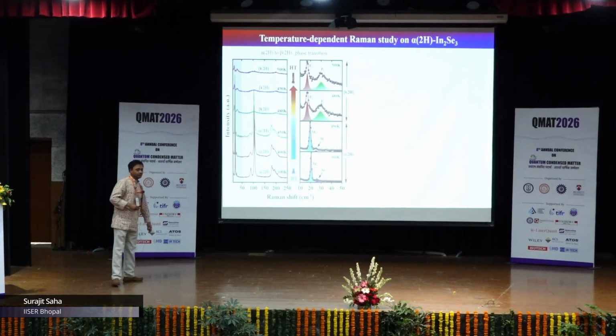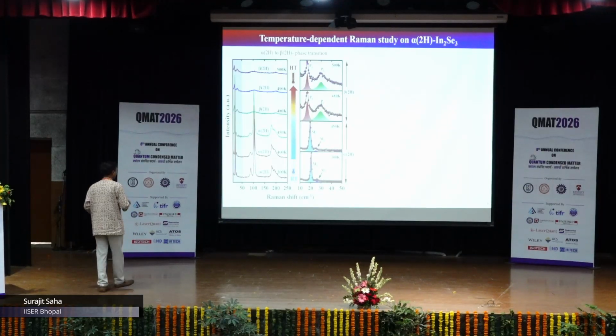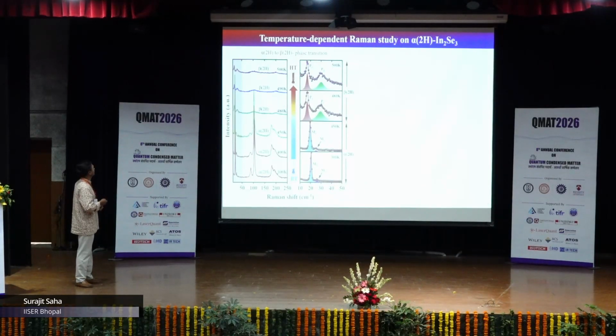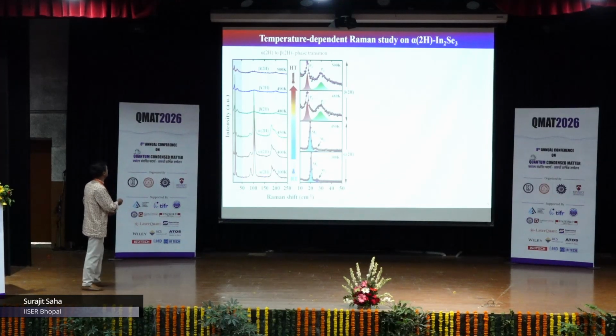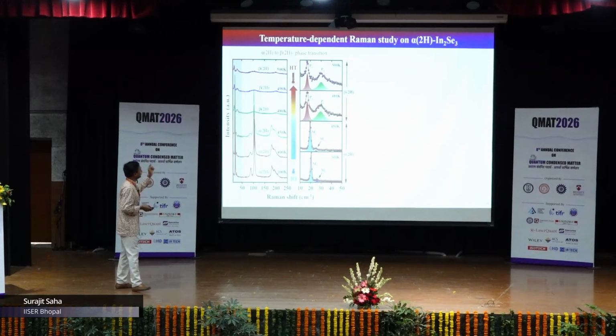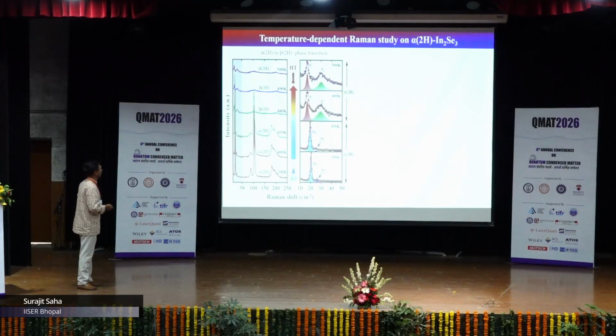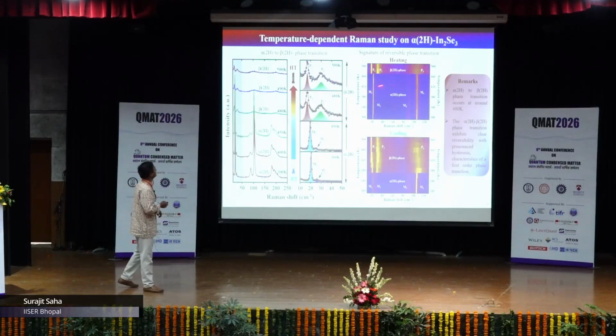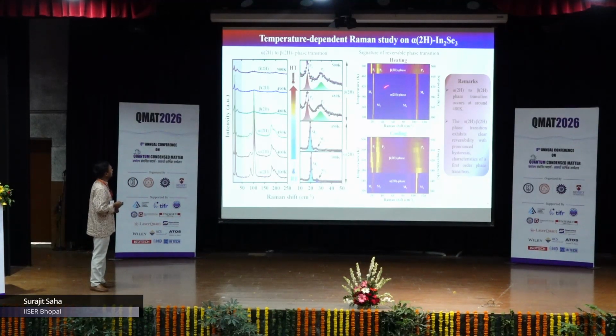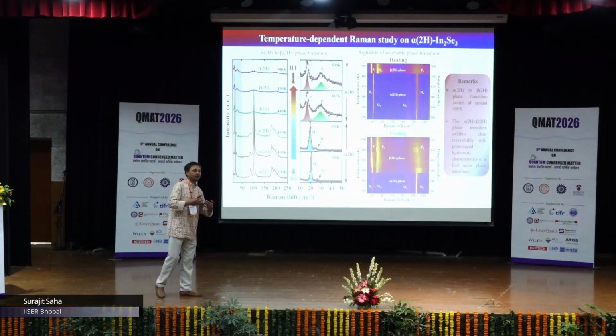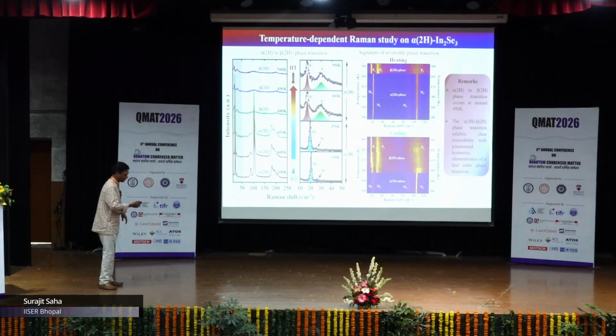the transitions. So we start from the room temperature stable phase, the alpha 2H phase. And as we heat this up to about 480 Kelvin, it starts to undergo the phase transition to the beta 2H phase. And if we limit our temperature to about 500 Kelvin, it retains the 2H phase. And if we cool down from that temperature, it comes back to 2H. Now there is a hysteresis. Here is the color map to look at this very clearly. So this is the heating cycle. You can see at about 470 Kelvin, the phase transition happens. And in the cooling, the phase actually comes back. It's a reversible transition, but the reversibility happens at a lower temperature, about 370 Kelvin. So the hysteresis, the width of the hysteretic transition, is about 100 Kelvin.